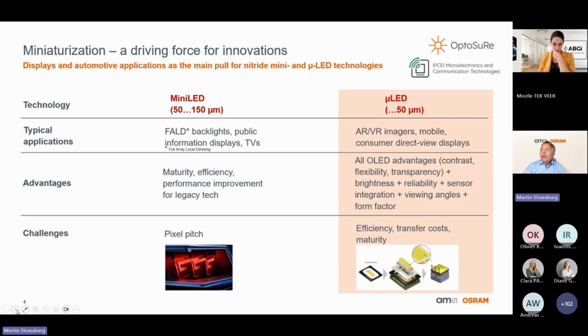And going even farther in the shrinkage, you can go to micro LEDs. These micro LEDs have a dimension up to 50 micrometers, but more important, if you go to the smaller limit, then you are typically around 1 micrometer or even below 1 micrometer. Typically, applications are here the AR, VR imagers, mobile applications, or consumer direct view displays, like for instance in smartwatches. And the advantages that come with this are really all the OLED advantages, maybe from the recent generation of direct view displays. So to say it's the contrast, the flexibility, transparency. And on top of that, now comes a high brightness, the reliability of the LED technology, the possibility of sensor integration, the better steering of the viewing angles, and the form factor.